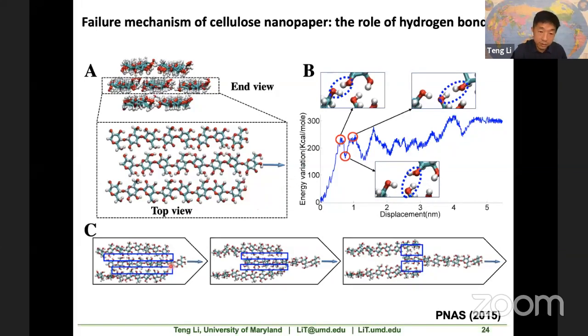So as illustrated here, during this sliding process, there were many cascade events of hydrogen bond formation, breaking, and reformation in these two boxes until it slides off. So although each individual hydrogen bond is not that strong, breaking it many times, if you add it up, that leads to a high energy consumption. So that leads to the higher toughness.